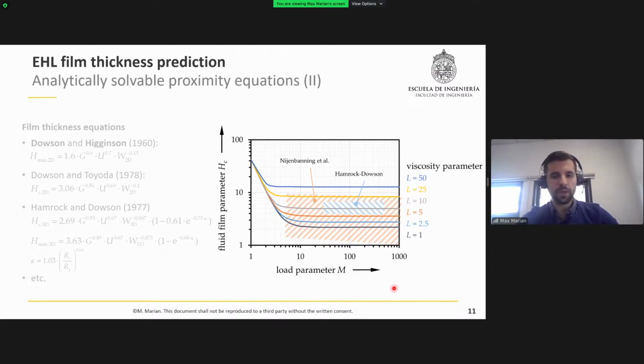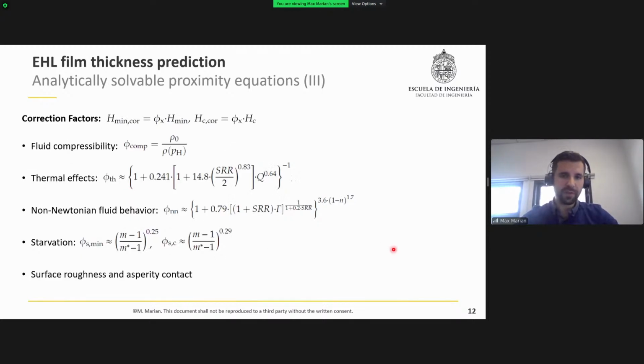However, there could be some deviations under certain conditions due to fluid compressibility, thermal effects, shear thinning, starvation, or also surface roughness. And all these aspects have not been fully considered in the original numerical solutions based upon which these kind of approximation equations were derived. But these effects can also be taken into account if we employ some kind of correction factors, φx, which are simply multiplied with the film height parameters to obtain a corrected fluid film thickness. In the original numerical solution, the density pressure relationship was modeled according to Dowson and Higginson, but the density was not considered as an input variable for the non-dimensional groups, and also not for the film thickness equations.